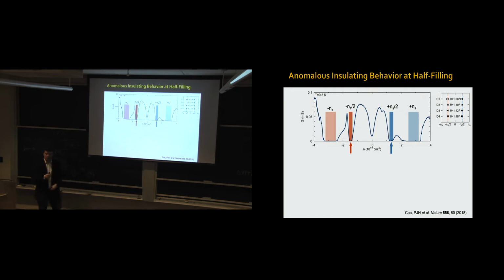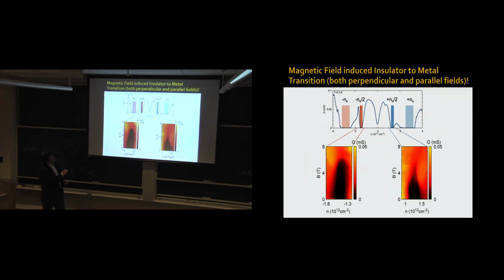The other thing that was very unusual is that if we apply a magnetic field to this system, it doesn't matter whether parallel or perpendicular to the graphene sheet, but it's more striking when we apply a perpendicular field: this insulator behavior turns into metallic behavior. If we measure the conductance near this region, black means insulator, red means metallic. As I apply a magnetic field, I go from insulator to metallic. Now that's extremely strange—a magnetic field makes electrons rotate, so it typically localizes electrons, it doesn't make them conduct better.